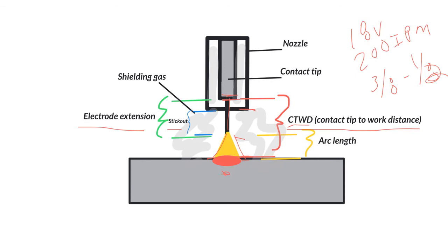Okay, to continue, we have stick out, and that is how much the wire sticks out beyond the actual nozzle. If you use a pair of welpers, which are weld helpers, pliers with a little wire cutting side to them, and you have that side farther away and then flush the pliers up to the nozzle, it'll cut the perfect stick out.